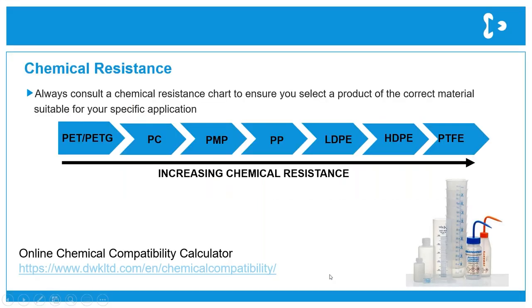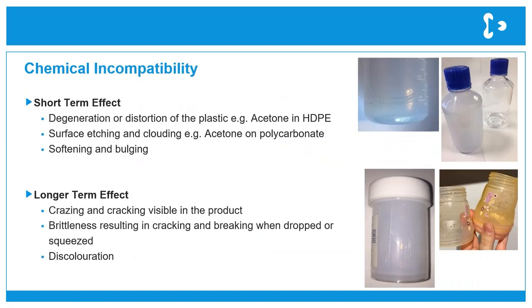So I'll go back to the presentation here now. There are implications in plastics of chemical incompatibility. There are some short-term effects. You can see here a polycarbonate bottle which has had acetone in it, and that's resulted in clouding. The bottle at the back is the original bottle, which has glass-like transparency, and the bottle at the front, which is not compatible with the acetone, has become cloudy. Polycarbonate is inherently a clear material, and that's the impact it has. You can also see a softening and bulging, which has distorted the bottle.